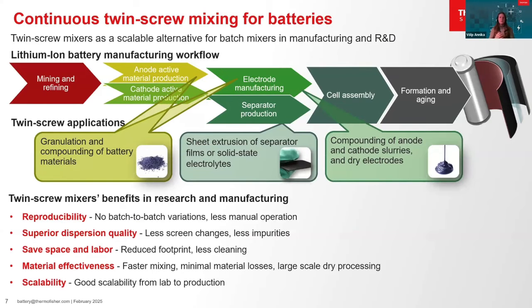For example, for compounding electrode active materials, twin screw mixers can be used for granulating silicon anode materials and fully solvent-free cathode materials. They are also used in the process of dry electrodes. Separator film production: conventionally, separator films are produced by extrusion, and it's a well-developed process. But for novel battery concepts such as solid-state batteries and gel polymer separators, lab-scale twin screw extruders are particularly beneficial.